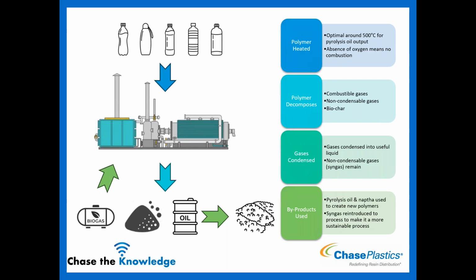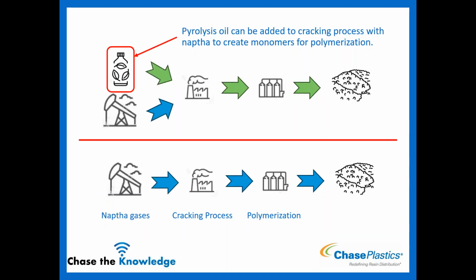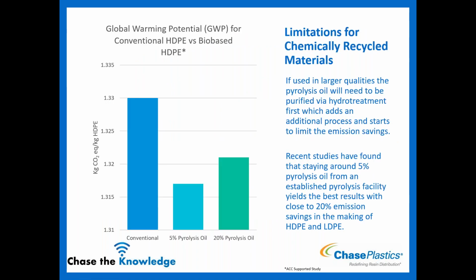So basically your syngas goes back in to heat the furnace to then heat the next section of material that you're going to use. And then we introduce the pyrolysis oil and naphtha back in to create new polymers. So that looks a little something like this. So your standard process would be your gases come in, then you have a cracking process, polymerization, polymer. In this case, when we're using bio-based ones with material that have gone through pyrolysis, you introduce the oil here with the gas, and then it goes through the same process, cracking, polymerization, polymer. And so that's what gives you your bio or green component, is using those gases from recycled material that already existed.